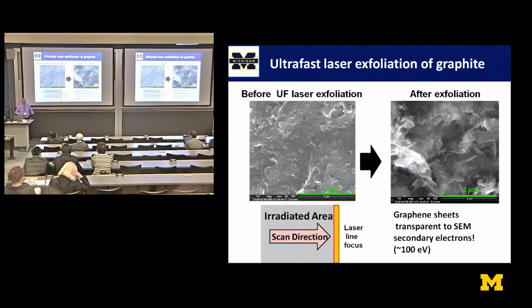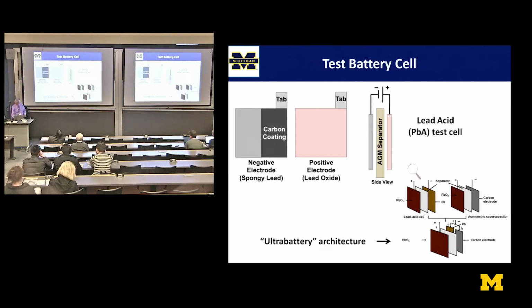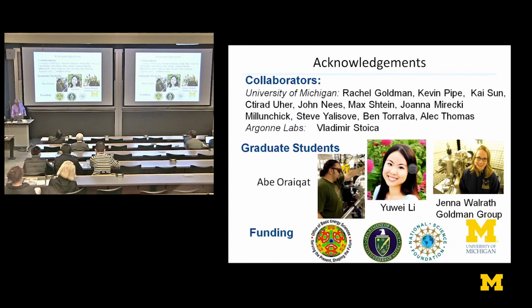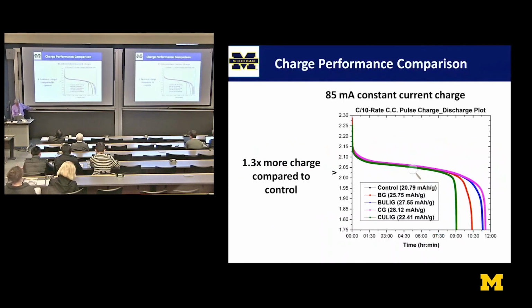This is an SEM picture of that, showing that we have transparent sheets with very, very large surface area. Some similar measurements show that the batteries can also store more charge when they have this kind of electrode produced with nano processed graphene.